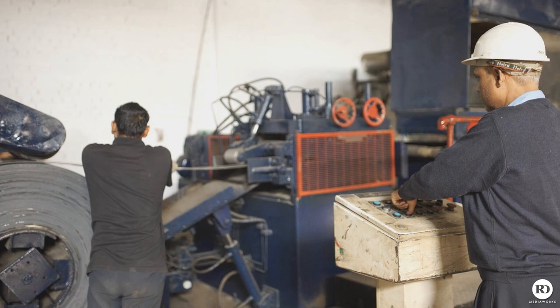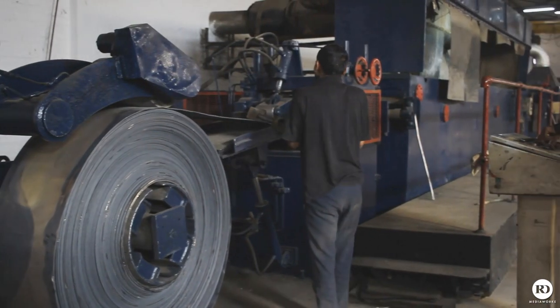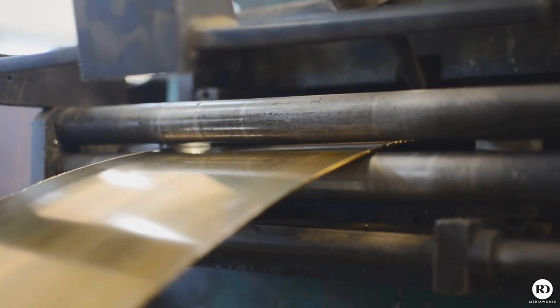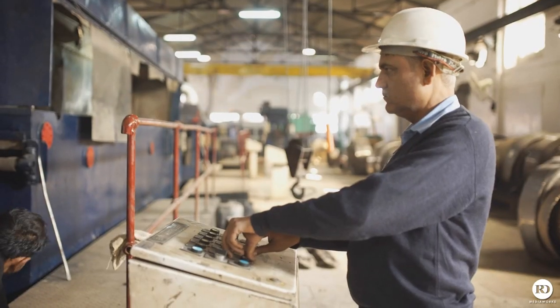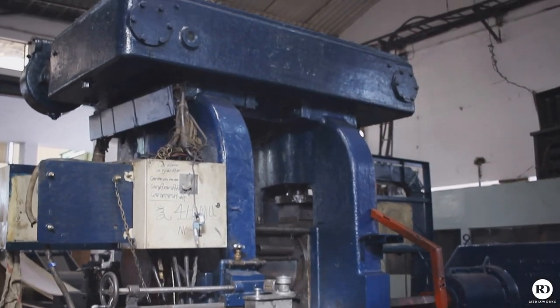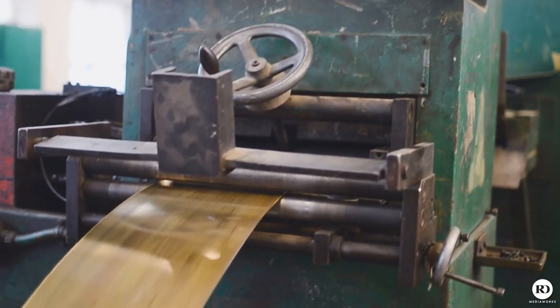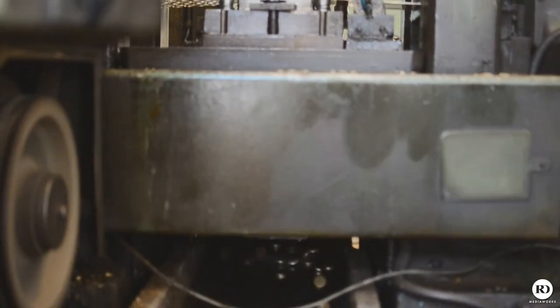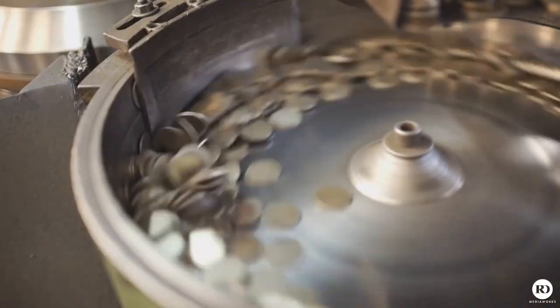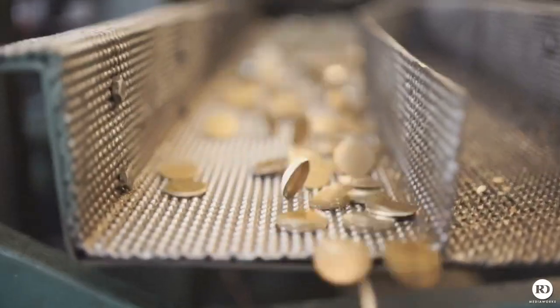The final rolling process is done from 3.5 mm to the final thickness, which for coinage alloys is normally between 1.2 to 1.8 mm. This thickness is achieved under a closed thickness monitoring system installed on our Farmer Norton finishing rolling mill. Ready-to-punch coils are made into disc blanks on high-speed presses by using carbide toolings. These blank discs are thereafter rimmed, an upsetting process on the circumference of the blank, which brings about edges to the disc. This process gives shape from a disc to a coin blank.